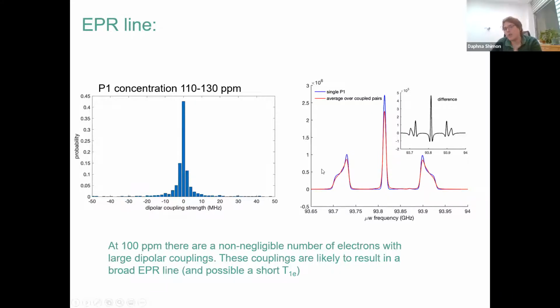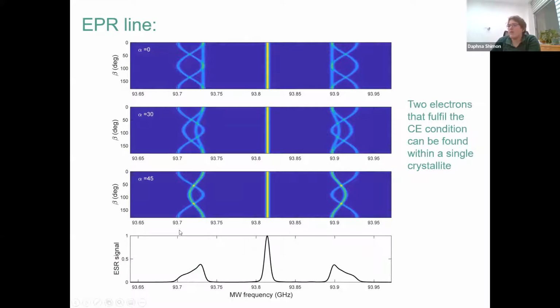But one good thing here is that from these results and from this slide, what we show is a single crystal of P1 showing the EPR lines as a function of the orientation of the crystal. So at different orientations, there are conditions where within the same crystallite, there are two transitions that can be separated by the nuclear Larmor frequency, or close to the Larmor frequency plus the dipolar interaction on the previous slide. And so at least we show here that there can be a cross effect within each crystallite. And so even if most of this broadening is from different crystallites, different orientations, we can still expect a cross effect.